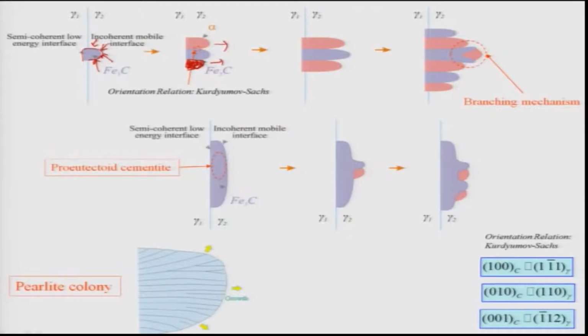And as growth of alpha requires rejection of carbon, it does not require any carbon, therefore nearby regions become rich in carbon, and this leads to further nucleation of the Fe3C. This is exactly how nucleation and growth of these phases happens, and this leads to colony formation. This is a colony, and as we have seen in the microstructure, the colonies form.